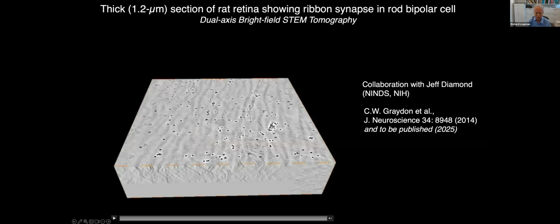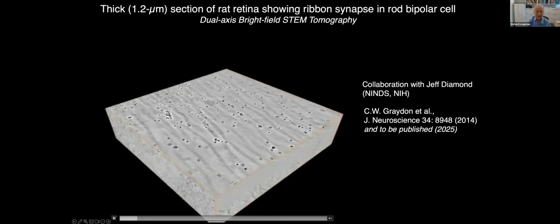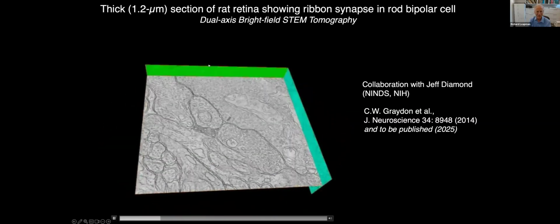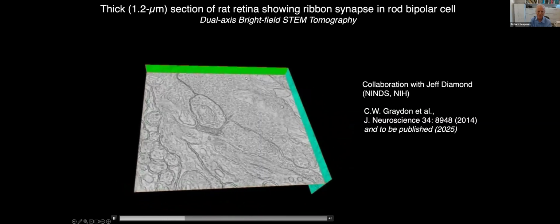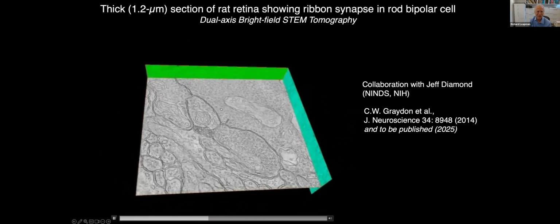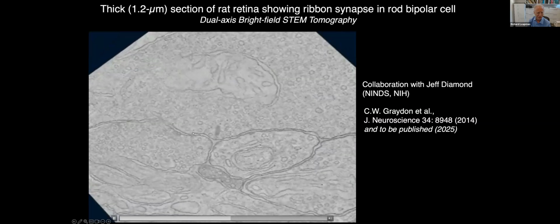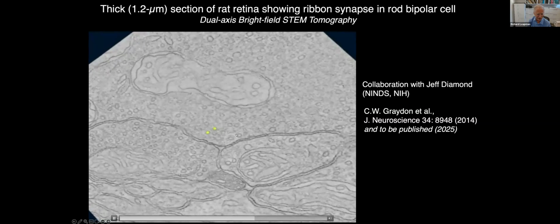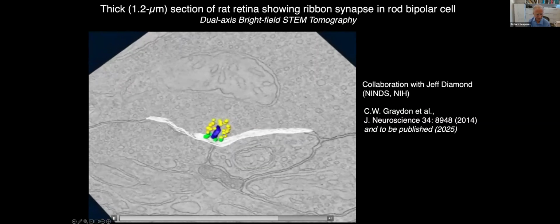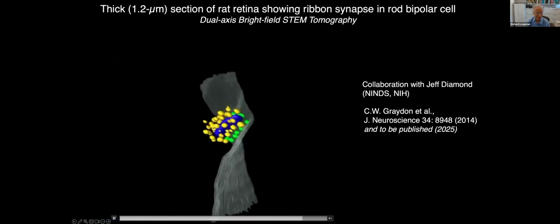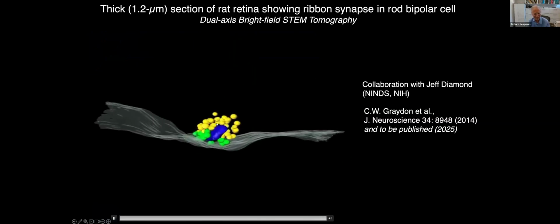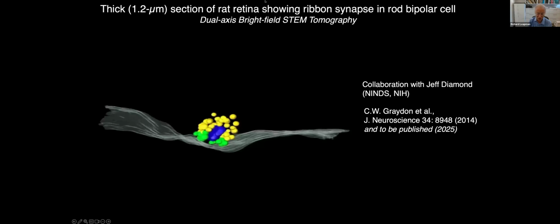And then this is an example of something that we did a number of years ago, but we have now taken this up again, and we're getting new data from the same system to ask some different questions. Here we see a 1.2 micron thick section of rat retina showing a structure known as the ribbon synapse in rod bipolar cells. The important thing is that this will become evident in the center of the image here, and this can be segmented here. But the important thing is these are very sparsely distributed synapses. They're not everywhere. You have to search around for them, but they're very, very important structures.